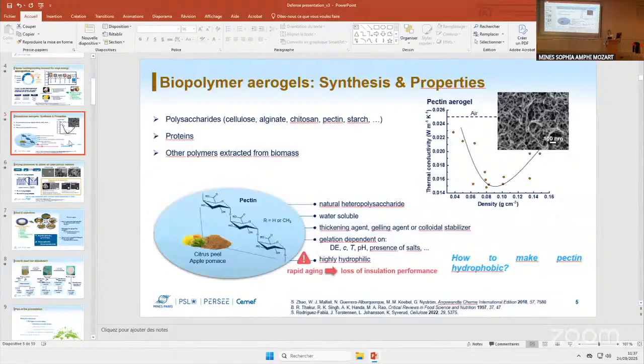Then you did these compression tests, and you lower thermal conductivity upon compression. So for me, this tells me you're on the left side of the density minimum, which is also what you would expect because of the densities you had. Is there a reason why you can't go to higher pectin concentrations initially?